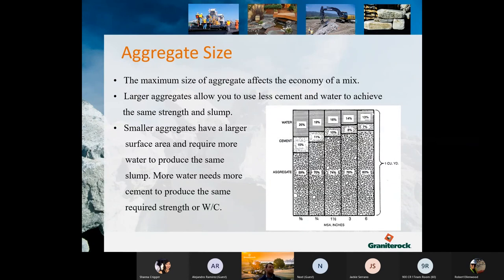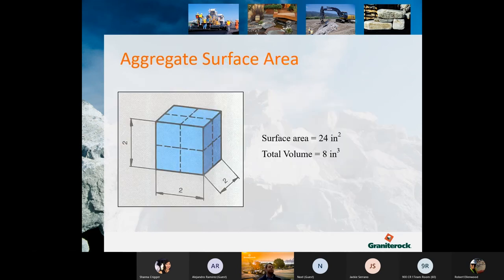This means more water to cement to produce the same required strength or water cement ratio. Basically, the smaller the aggregate, the more cement you need, which means more water. So you get a better idea.